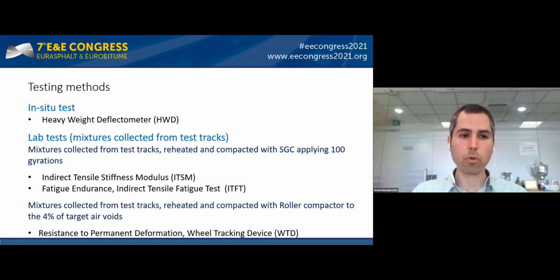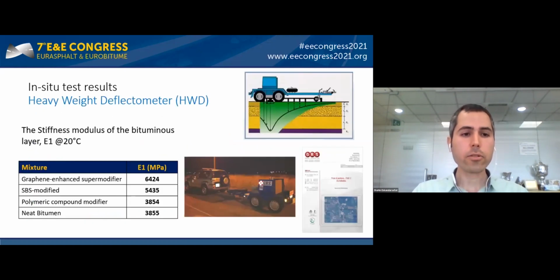The testing plan included both in-situ tests and lab scale tests. During the in-situ tests, we used a heavy weight deflectometer, and during the lab scale tests, the mixtures were investigated by means of modulus, fatigue endurance, and resistance to permanent deformation. During the in-situ test, the heavy weight deflectometer was run at 20 degrees centigrade, more or less the temperature. According to this table, you can see the modulus of the mixture containing the graphene enhanced super modifier was almost double when compared to the neat bitumen, and comparable or superior to the other two tested mixtures in this study.